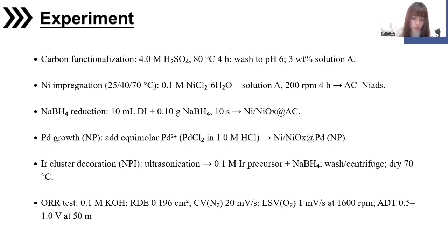In step 2, rapid sodium borohydride reduction forms nickel nanoparticles, which partially oxidize to nickel and nickel oxide. After that, the equimolar palladium precursor solution is added, allowing palladium nanoparticles to grow on the NiOx supports. This product is referred to as NP.